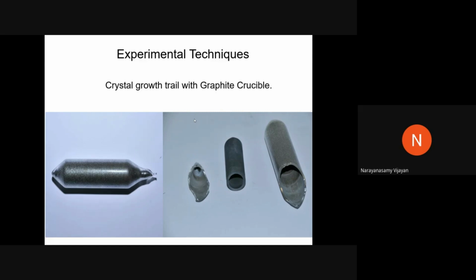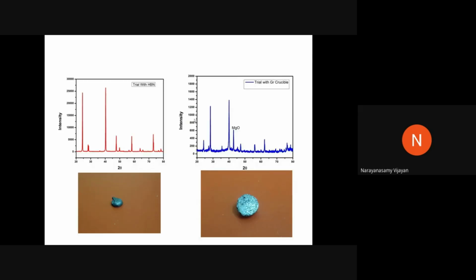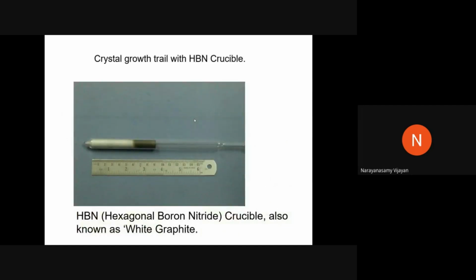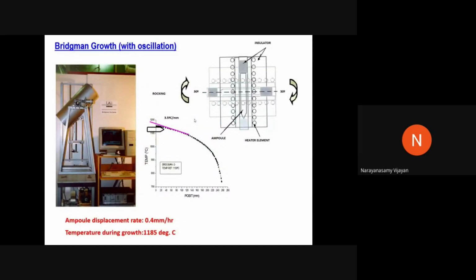You can see graphite crucibles we have taken, and then we studied what the content is in a failure, and what the content is if it is a success. So through various characteristic analyses we have grown. And then an HBN crucible also we have taken, because the outside crucible is quartz, and inside is the HBN crucible, that is hexagonal boron nitride crucible, that is called white graphite.